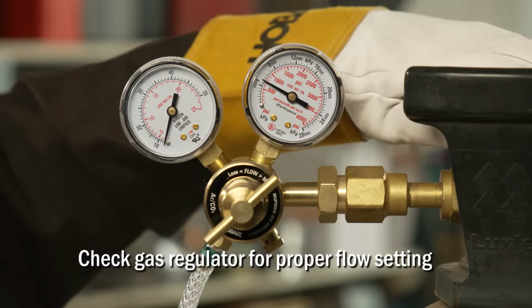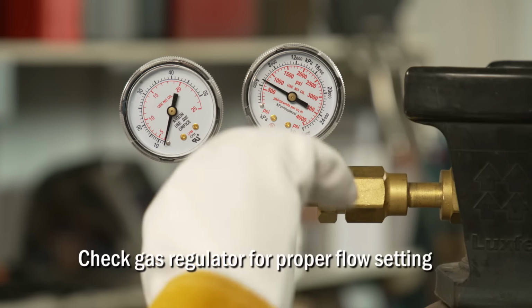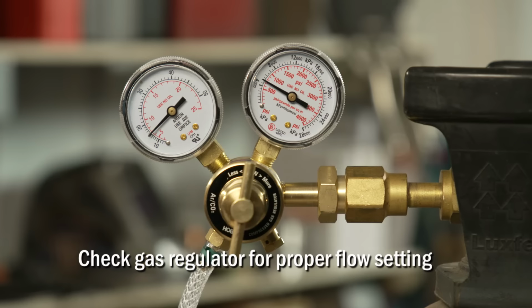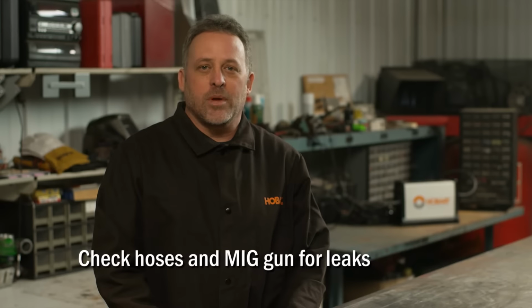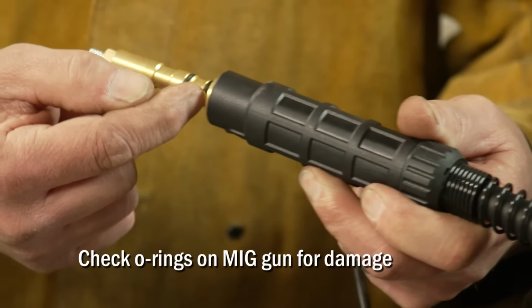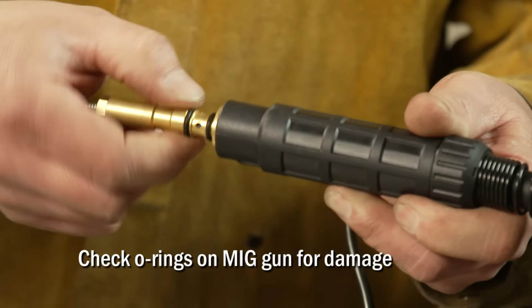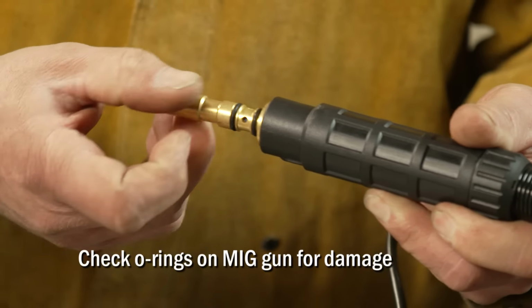First, check your regulator to make sure you are not out of gas or your gas flow was set improperly. Adjust as necessary. Next, check your hoses and MIG gun for leaks. Another item to check for leaks is the O-rings on the pin end of the gun. If there are pieces missing, replace the O-rings.